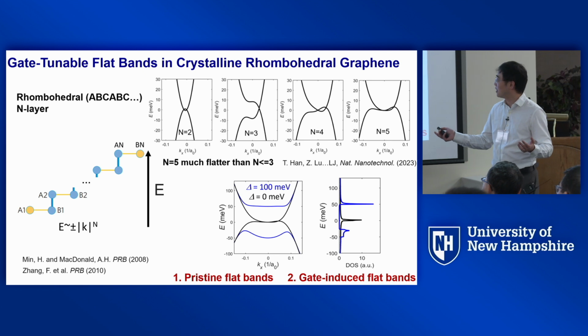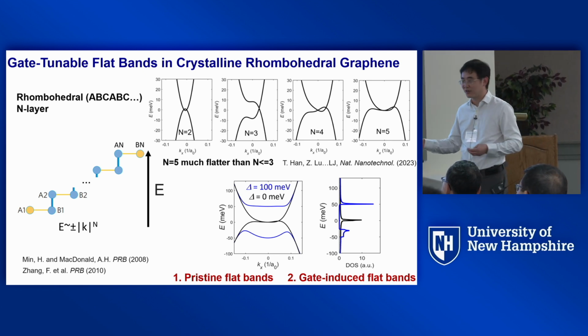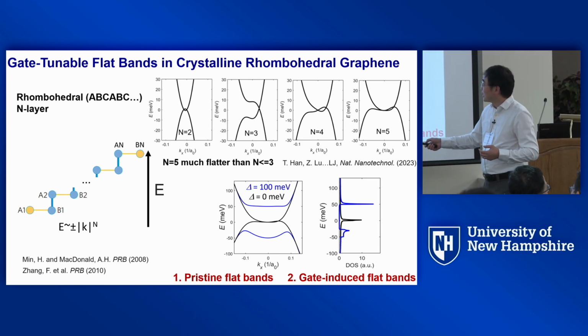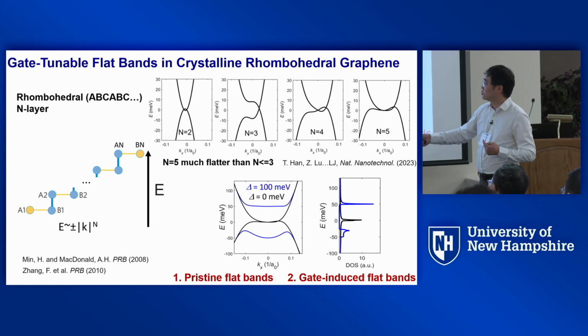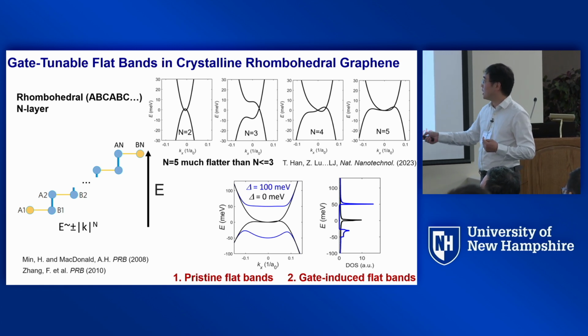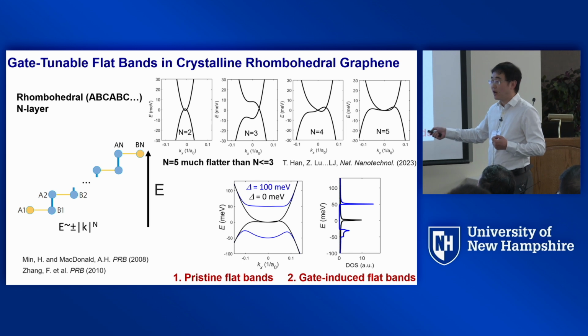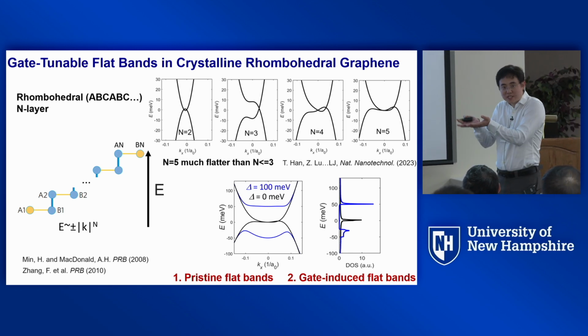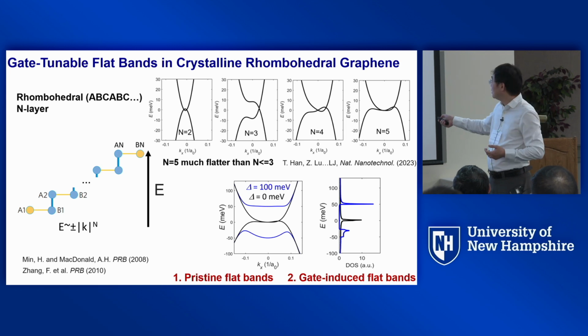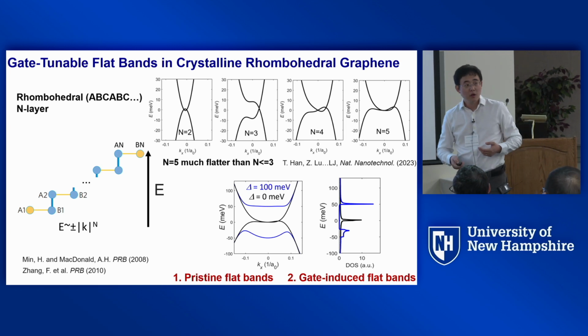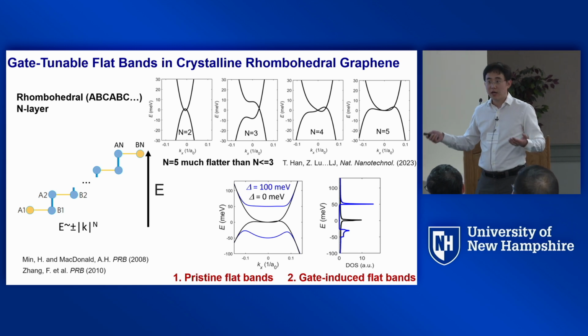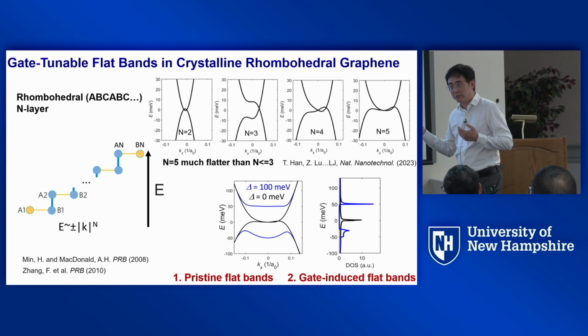Okay? And this structure has another advantage, which was actually pioneered by Alan too. In 2D, it's really hard to give a talk without citing Alan's work. That you can further tune the band structure by applying a vertical electric field to break the symmetry between A1 and Bn. As a result, you can open up a band gap where the band is already flat, and you can make it even more flat by squeezing the bottom of the conduction band. You get an even bigger density of states corresponding to this flat part here. Okay, so crystalline graphene has an electrically tunable flat band.